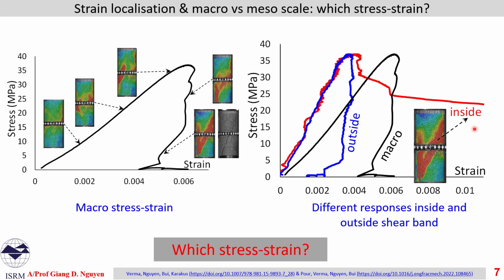And if we plot the macro stress against strain, inside the shear band, the red one here, outside the shear band, and the macro, the black one, we see three distinct behaviors: unloading outside the shear band, the blue one, and strain intensifying inside the shear band, the red one. The macro one is in fact the rolling average. In this case, we cannot use the volume average one to represent the behavior of the material.